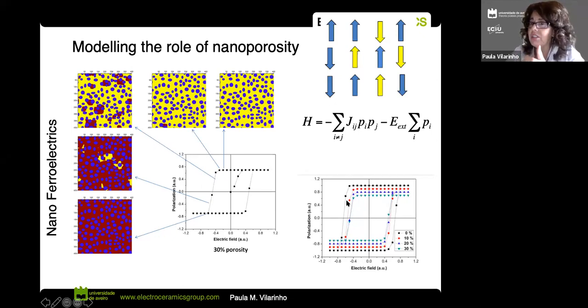So what we discovered was, if we have porosity that is smaller than the domain size, this porosity will help the switching of the polarization. And as you can see here, as we increase the porosity, our coercive field, that is exactly the measure that tells us about the switching, is really decreasing.